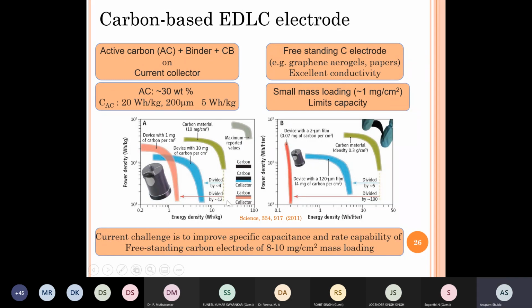Okay, and if the carbon loading is much smaller, then the collector remains the same. So therefore, the weight of the current collector becomes a much higher fraction than the active material. Then the value will come down to what is here on the orange curve. So there is a lot of difference between the energy density of active material and the energy density of the real electrode, based on how large the loading of the active material or the thickness of the